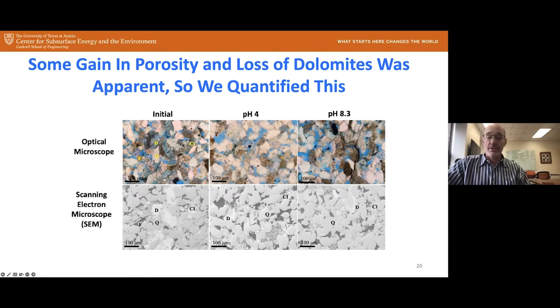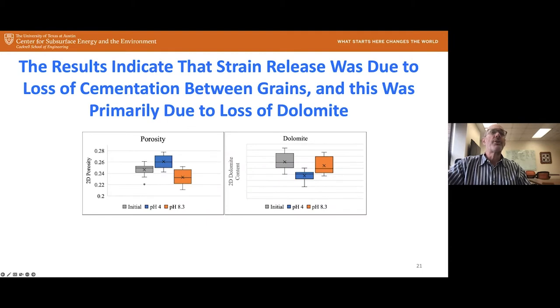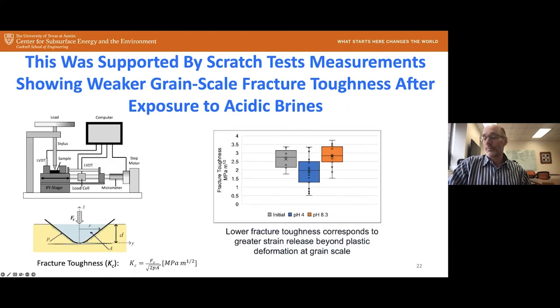So we took many of these images and quantified that. There's two things we quantified. One was the porosity and the other was the amount of dolomite present. And what we found, in support of our general observations, when we looked at many images and quantified this, was a higher porosity from the experiment that was exposed to pH 4, the lower pH, and we also got lower dolomite. So this is showing that, yes, this lower pH solution was dissolving the dolomite. Yes, it was creating a higher porosity, and that's related to this faster strain release at the lower pH.